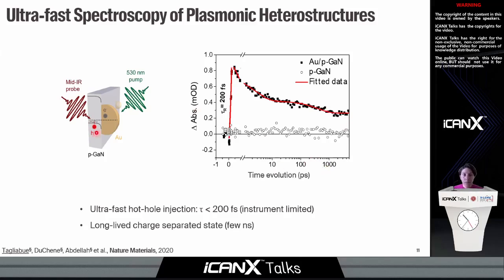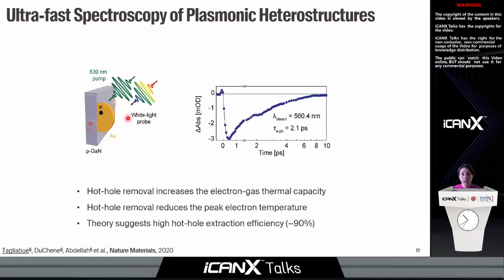At the same time, this is telling us about the fate of the hot holes, but we also wanted to understand more about the fate of these hot electrons that are remaining behind in the metal, and that in a real situation, we would expect to transfer to a certain degree to the adsorbed CO2 molecules. So we use the exact same sample and perform a second ultrafast spectroscopy measurement, where now we use a white light probe that probes the population of the electrons and the electron dynamics in the metal.